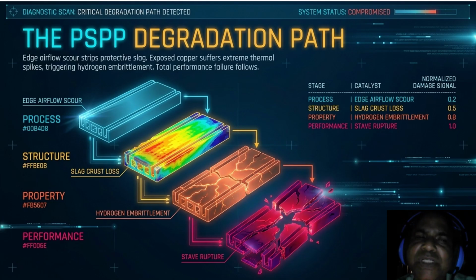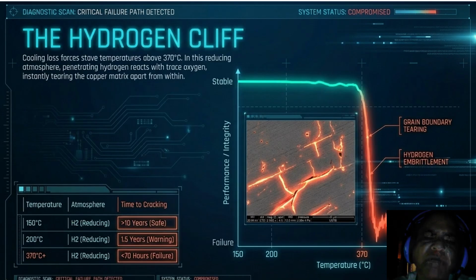If you want to intercept this failure, we have to look closer at the chemical tipping point known as the hydrogen cliff. The most dangerous point in this sequence occurs when the copper reaches a specific lethal temperature. Our next slide shows the hydrogen cliff. This is the most important chart you will see today. Performance integrity is plotted against temperature. Notice the stable line up to about 150 degrees Celsius. We are in a safe 10-year-plus zone. But follow that line to the 370-degree mark. It doesn't just dip, it plummets.